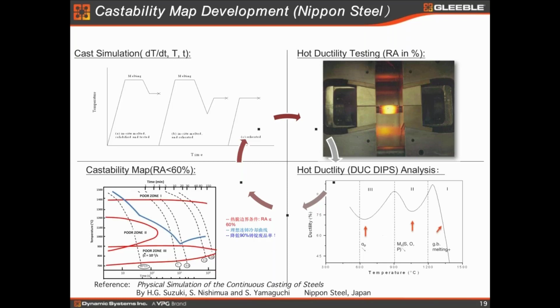So at the Nippon Steel, they use SEM, of course. I always say the Gleeble is the bullet making machine, and SEM is just the machine that takes the Gleeble sample as a bullet. Without a bullet, the machine gun or the SEM is useless in a certain way. So Gleeble can generate lots of samples for your SEM, which makes it even more useful. So to study the origin of the low ductility, you need to check the fracture surface. By examining the fracture surface, you know why there is a low ductility.